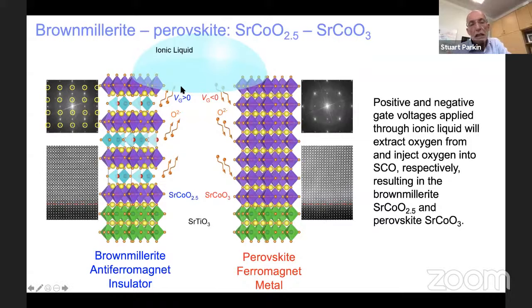And then using this ionic liquid, we can convert this structure to the structure on the left-hand side, which I hope you can see. You can see alternating dark and light regions, corresponding to alternating layers where we've removed half of the oxygen. So you form an ordered arrangement of oxygen vacancies, in this case parallel to the strontium titanate. It turns out the one on the left, the strontium cobalt oxide SrCoO2.5, is called a brownmillerite. It's antiferromagnetic and it's an insulator. And the material on the right-hand side is perovskite, it's metallic, and it's ferromagnetic.